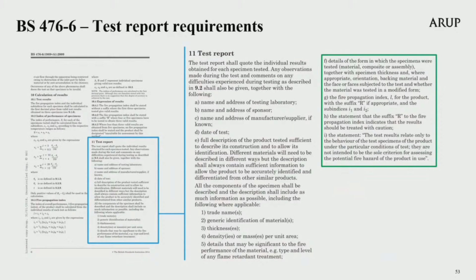The standard specifies the required contents of the test report. I particularly note the report must state details of the form in which the specimens were tested, material, composite or assembly, together with specimen thickness and, where appropriate, orientation, the backing material and the face or faces subjected to the test, and whether the material was tested in a modified form.